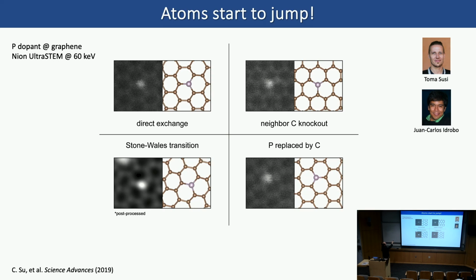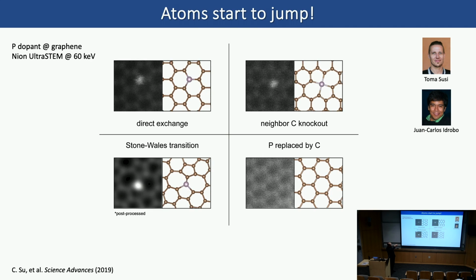But in this case, I used phosphorus-doped graphene, and I look at this single phosphorus dopant, and you could see that under the beam scanning, this little dopant is actually going through a lot of dynamics. In this case, it's what we call direct exchange, where the phosphorus atom exchanges sites with the neighbor carbon atom, and the Stone-Wales transition is basically rotating by 90 degrees at a time.